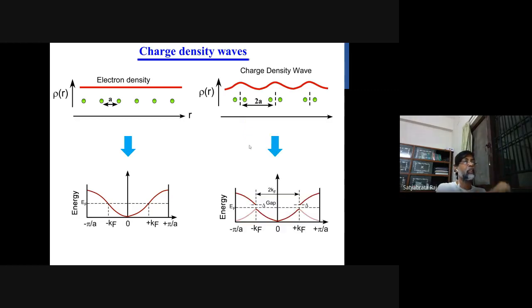Then what will happen? Your new lattice constant becomes 2A, and if your KF is just half of pi by A, then your new Brillouin zone will be reduced to half. As a result, you will open up a band gap at the new zone boundary, and the system will go to an insulating phase. That is the charge density wave. So this becomes the new zone boundary, and you have a gap at the new zone boundary, and the system becomes insulating.